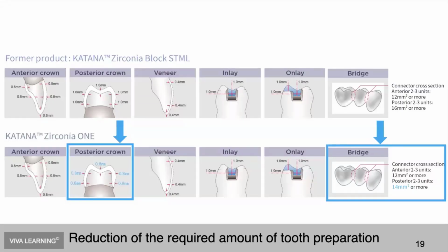So you can see on the top where the STML is, yes, we can do anterior crowns down to 0.8, posterior crowns down to 1.0. We can do veneers as thin as 0.4. I would highly recommend you bond those in, and we'll talk about the bonding techniques that we use. We have inlays, we have onlays, and then the big change to Zirconia 1 is we've increased how strong it is while also decreasing the reduction in the posterior. We only need 0.8 millimeters of reduction.